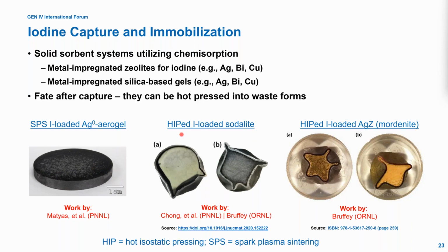And then this is a hot isostatically pressed iodine loaded sodalite material that was made at PNNL. The hipping was done at ORNL by Stephanie Bruffey. And then this is some work by Stephanie Bruffey where she's taken iodine loaded silver mordenite and she's added different amounts of binders and hot pressed that with HIP.